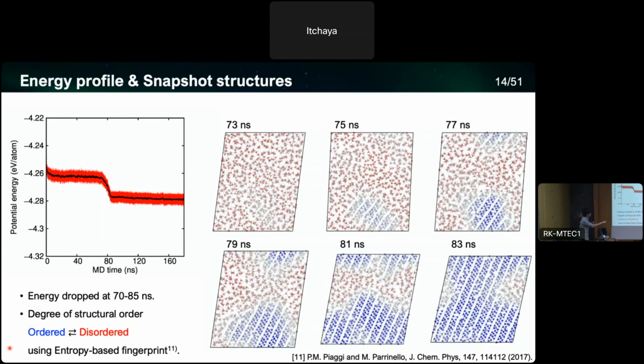We can see some of the white colored region, and it expands and grows as time proceeds. And from 79 to 81 nanoseconds, the crystalline nucleus connected in the lateral directions. Afterward, it extends toward the lateral direction, not the vertical direction. And at 83 nanoseconds, it finally connected toward this direction as well. And at 85 nanoseconds, the crystalline region has already extended to the entire part of the supercell.